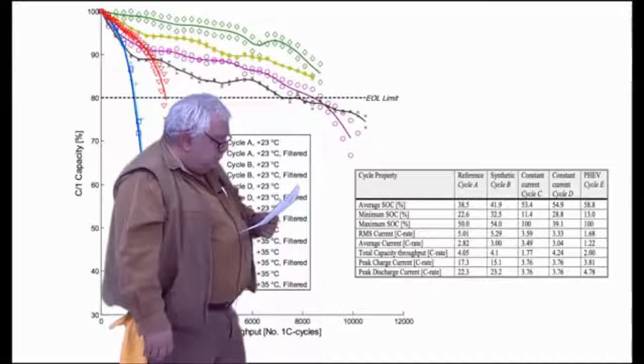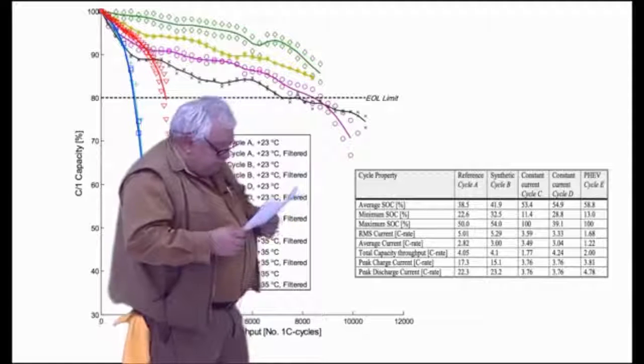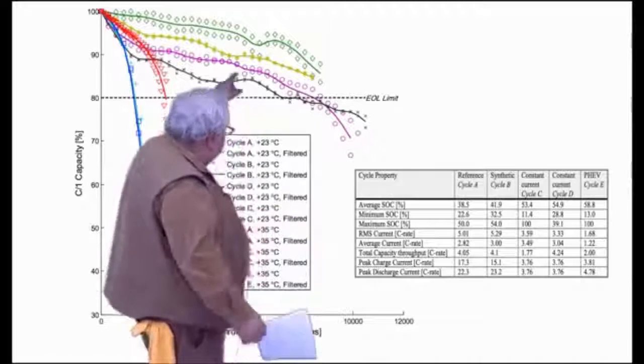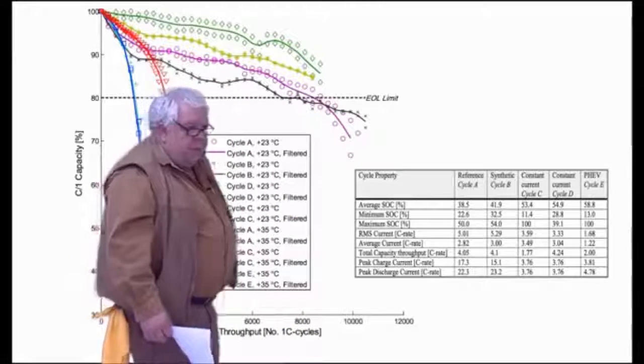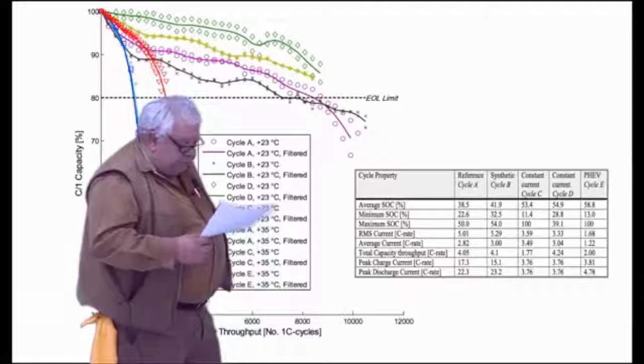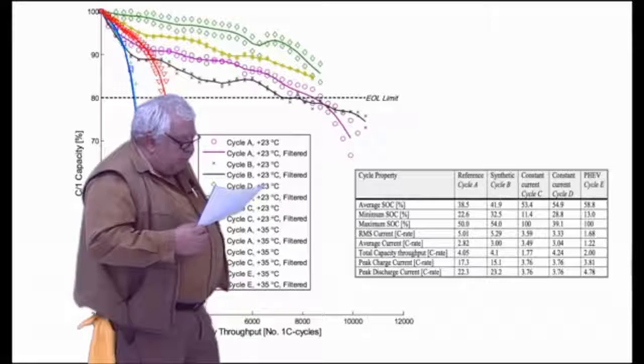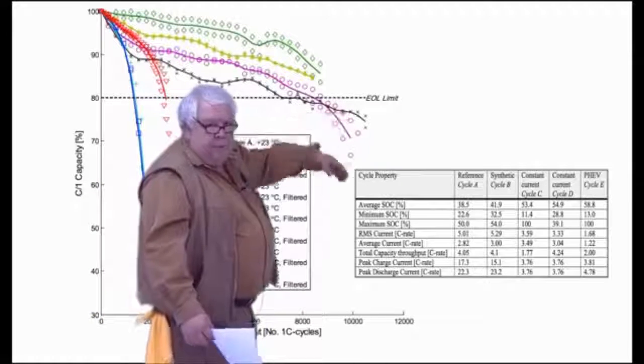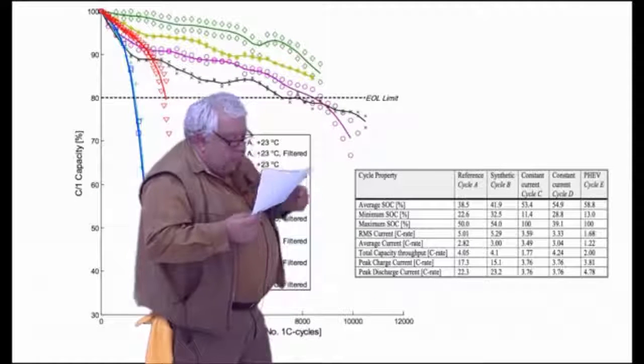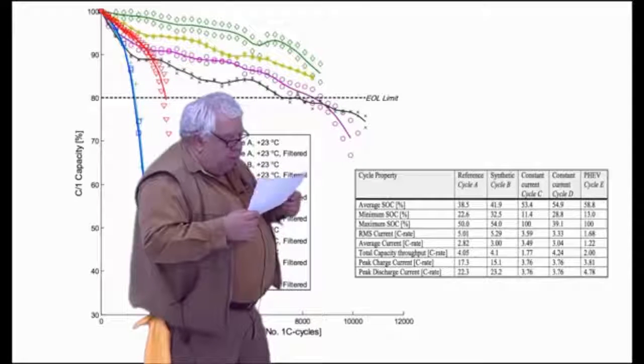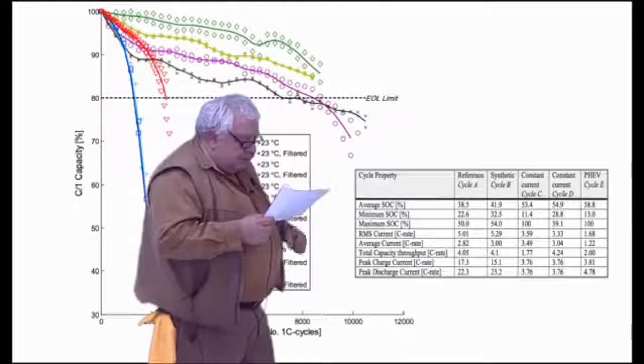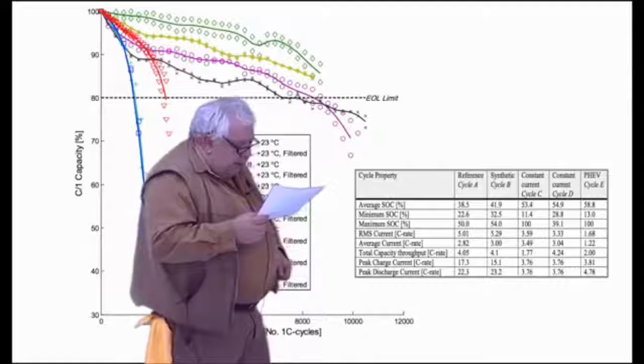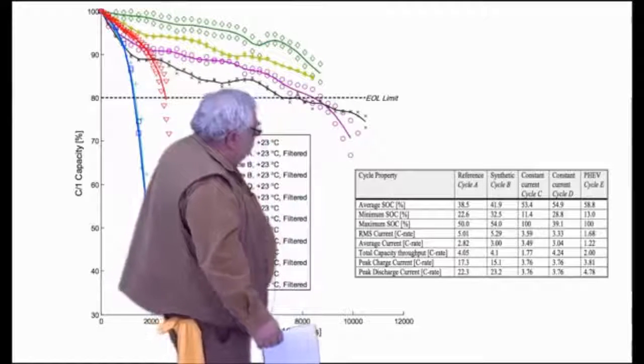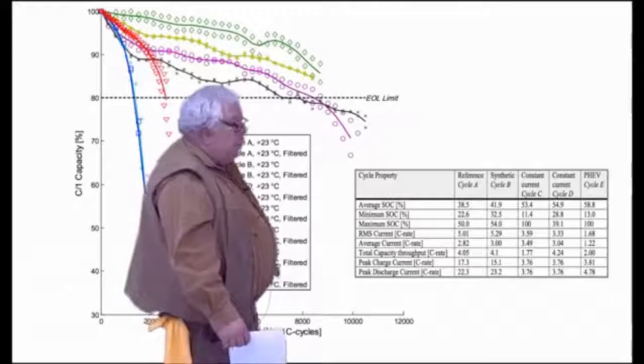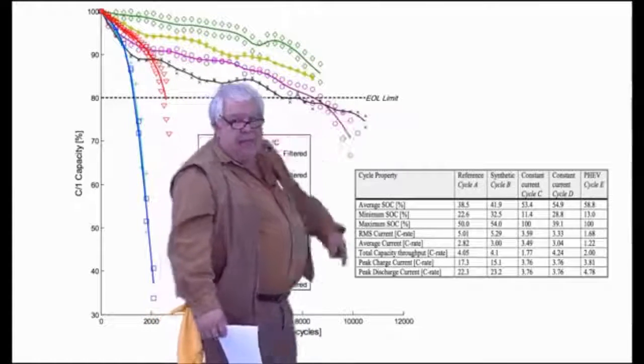He only fully charges it on the dots here, circles and triangles, the green and the purple, where he stops and measures capacity of the cell. At 9,000 cycles, we're still about 85% on the green one, and we cross 80% right at about 9,000 cycles on the purple one. Let's talk about that for a minute. The purple one is at 23 degrees centigrade. The green one is in a climate box at 35 degrees centigrade.